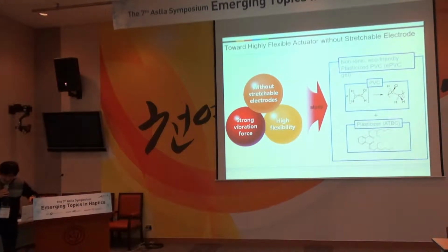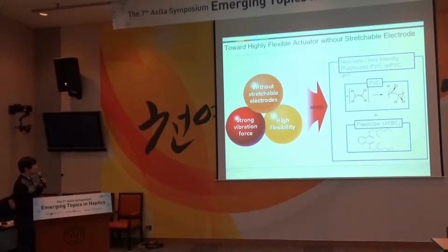And as I said before, the problem is the stretchable electrode. So we studied some material. The reason is that we really want to get a soft actuator without any flexible and stretchable electrode, so it can create a strong vibration force and has very high flexibility. Based on the study, we found that the plasticized PVC does not need any flexible electrode.